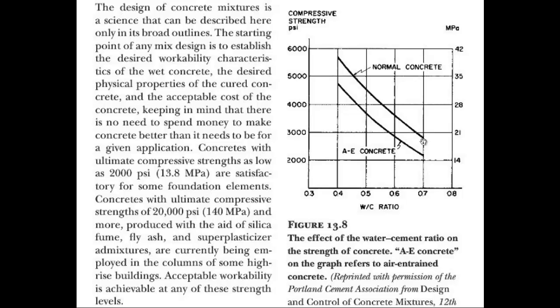The less water used, the more strength you get from the concrete, but it is more difficult to place because you get a much stiffer material. If you're looking for 3,000 PSI concrete after 28 days, you're going to be looking at just under a 0.6 water-to-cement ratio.